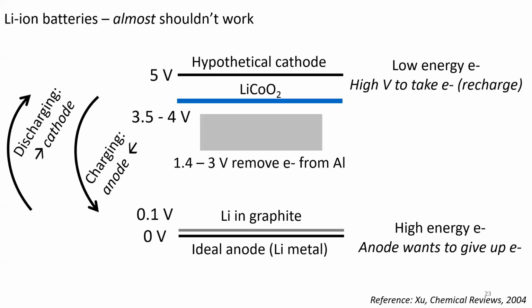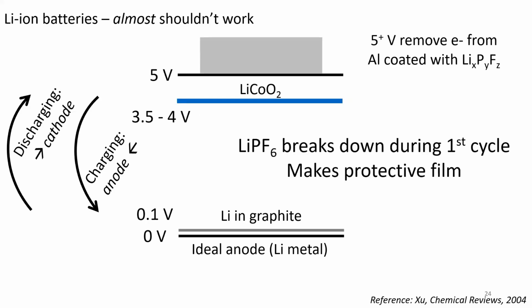So that's why I put this range of values, because the aluminum oxide stabilizes the aluminum a little bit. But that protective aluminum oxide that lets us use bare aluminum in everyday life is not enough for the extreme voltages in our battery. But if we have LiPF6 as our electrolyte, when it's in the battery and we go through the first charge, a small amount of that LiPF6 breaks down on the aluminum current collector and makes a protective film that's even better than aluminum oxide is.